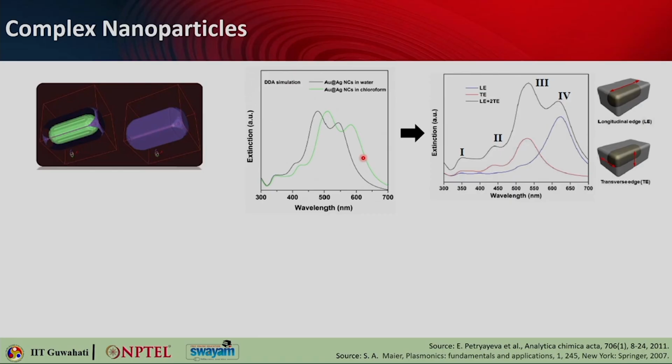So that is what you can expect, that this nanoparticle resonance is very much dependent on the surrounding permittivity. So they all can actually act as a refractive index sensor. One more thing is that you can also do a thorough analysis of these different peak positions. You see there are 4 different peaks. So when you see these peak positions, you can see what is basically creating these peaks.